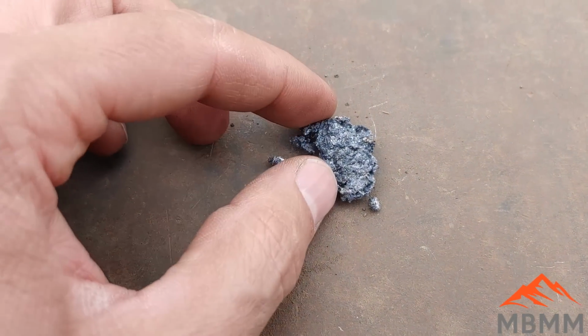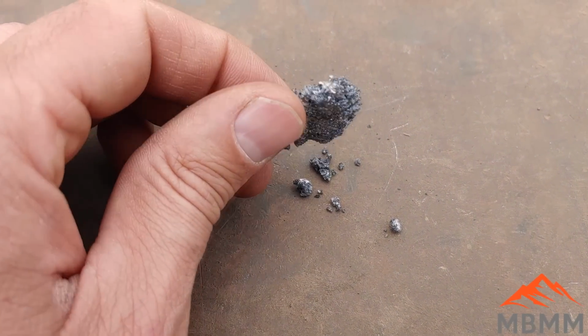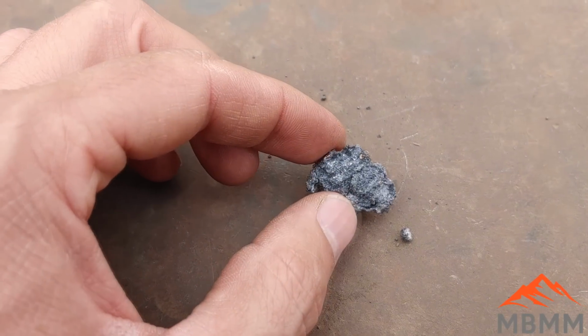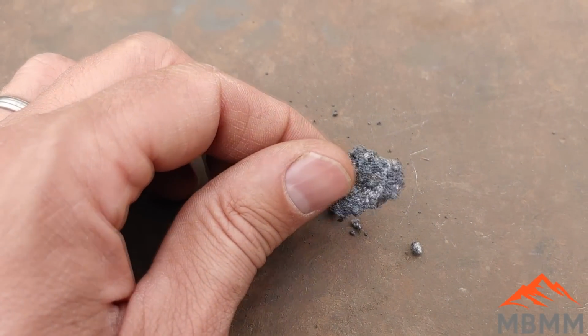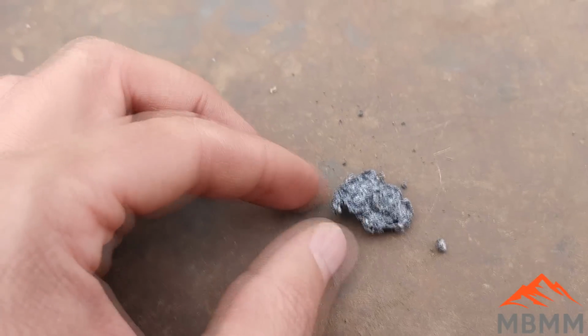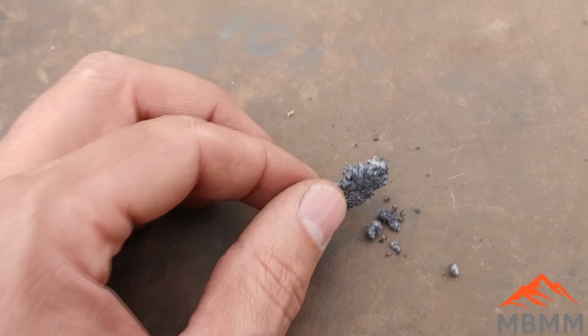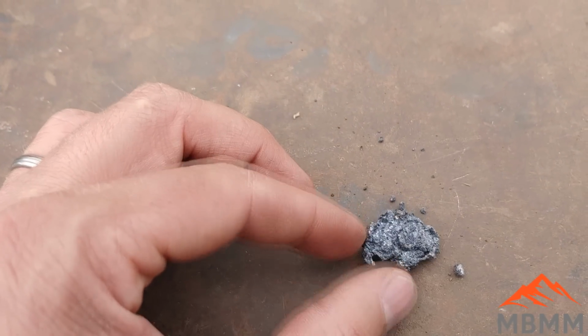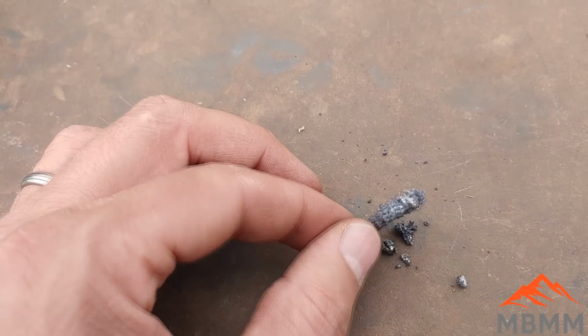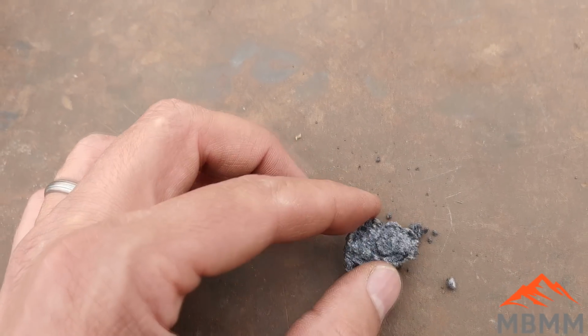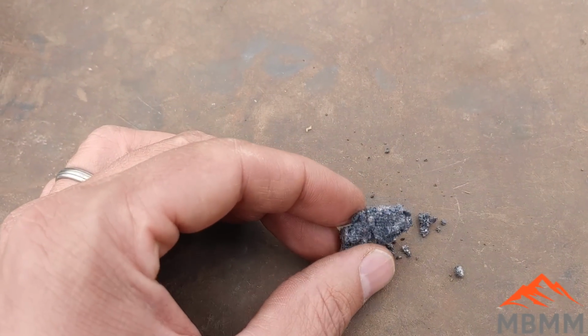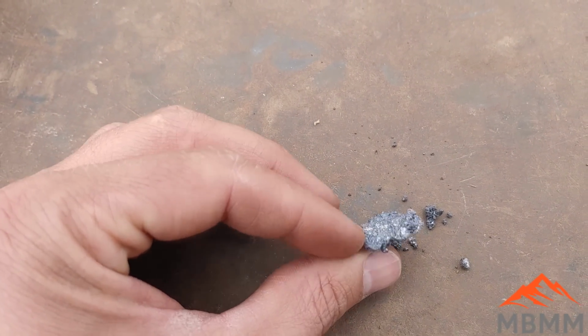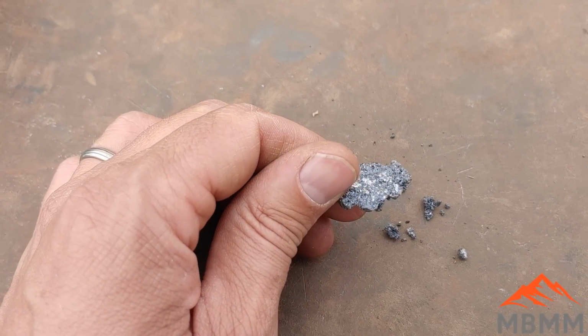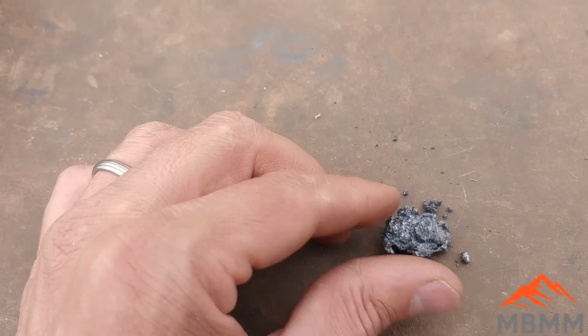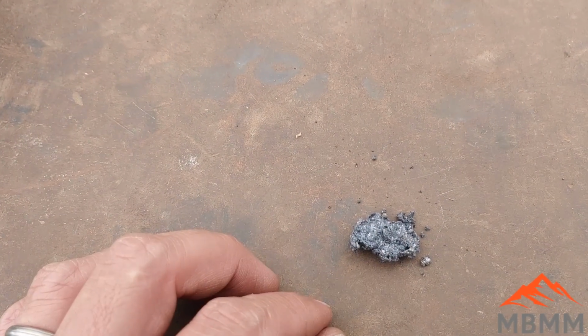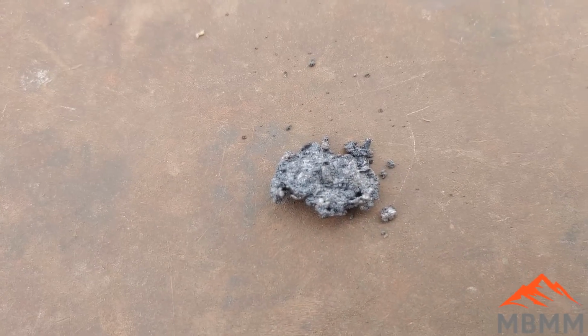And here's a bunch of that oxide slag junk that was floating on top of our lead bead. And so I just pulled the cupel out of the furnace, scraped it off, and we can throw this in our next smelt and get it all oxidized and absorbed into our slag so we don't lose anything. But that's probably those base metals, the copper and some other junk that we had from the matte, and we got it all out of there. And now our lead's in the furnace, cupeling away.